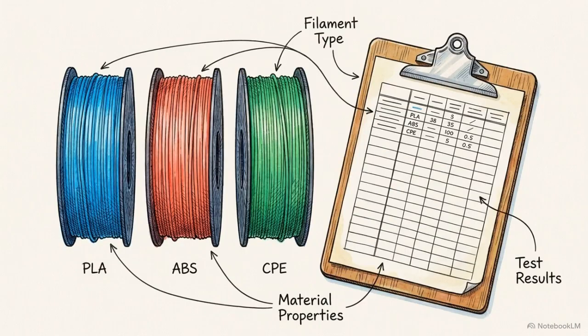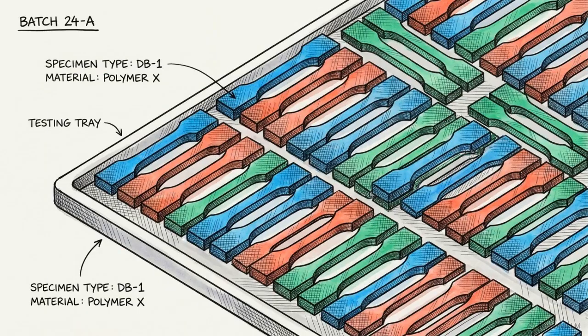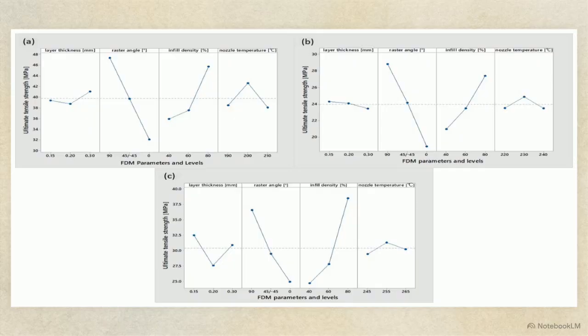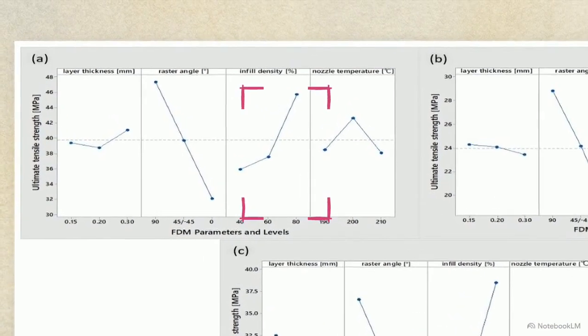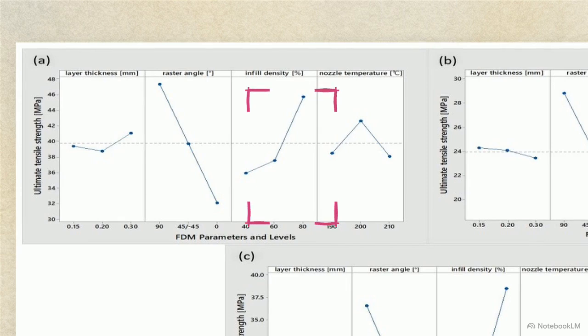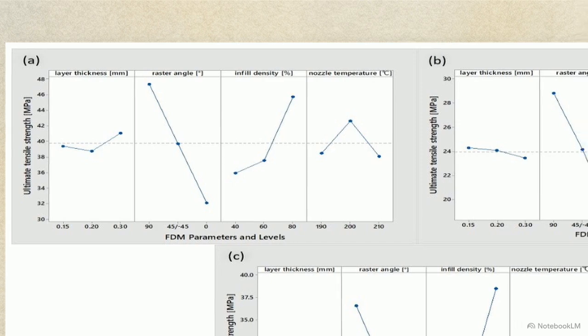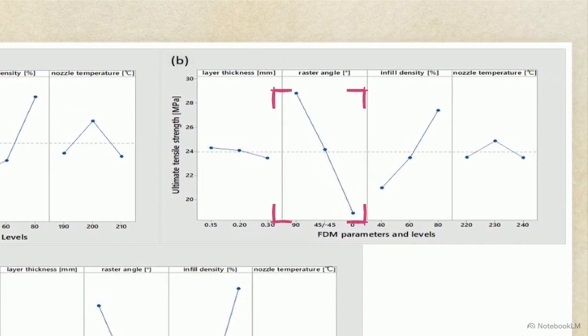To isolate the variables, researchers structured a Taguchi Design of Experiments, executing a systematic series of test prints across the PLA, ABS, and CPE materials. These main effect plots track how each physical printing parameter influences the ultimate tensile strength of the specimens. The data isolates the dominant impact of mass density on structural integrity. Increasing the infill density from 40% to 80% boosts raw tensile strength by 27% in PLA, 30% in ABS, and nearly 56% in CPE. Beyond simple mass, orientation governs how the part bears a load.